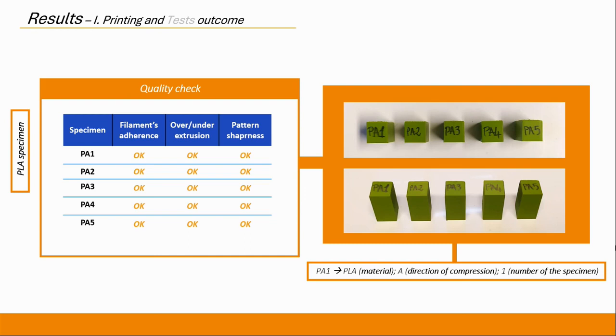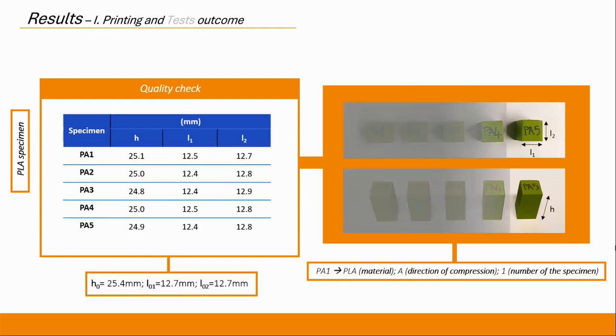After a more detailed control, we notice that the first few layers printed on the supporting raft have an infill density lower than 100%, about 80%. This aspect highlights how the software used to design and generate the G-code does not take into consideration the limits of the machine used. The dimensional errors on the specimen are acceptable based on the printing properties.